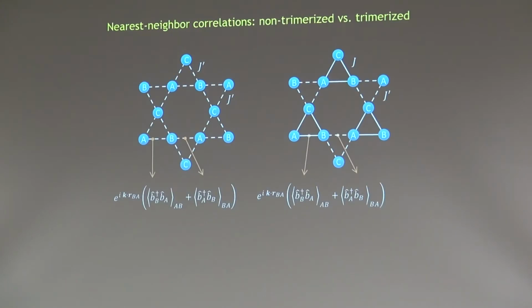All right, so what will that look like for atoms expanding out of either a trimerized or non-trimerized lattice? Here's, let's say, a regular Kagome lattice where we're going to drive the system into the deep Mott insulating limit by reducing the strength of all of these bonds by the same measure. Or we'll work in the trimerized Kagome lattice and we'll drive the Mott insulating transition by reducing the strength of these weakly coupled bonds, but we'll let the strongly coupled bonds remain strong and at constant strength.